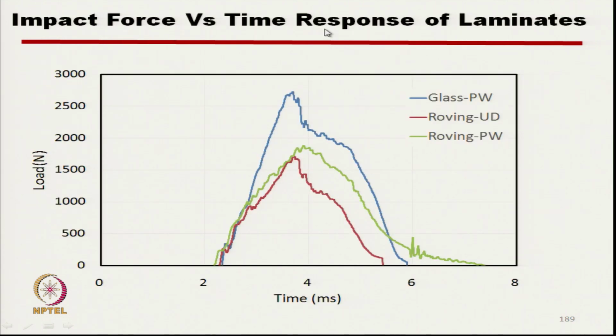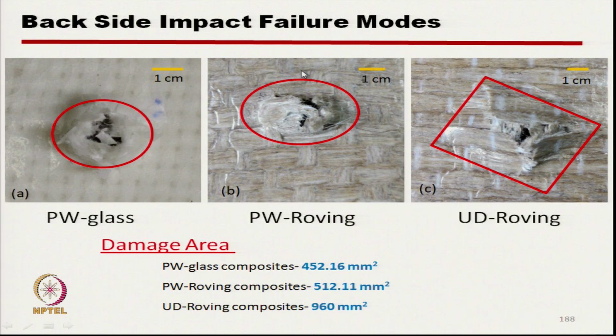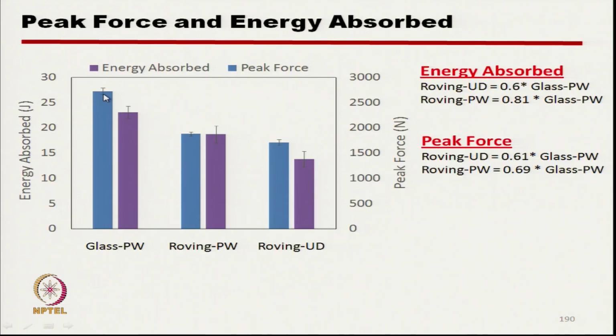In the impact load versus time response, the impact load is higher for glass, followed by plain woven roving, and unidirectional roving is behaving in an inferior manner, as we saw in the earlier picture. Unidirectional roving gives a higher damage area. Regarding peak force and energy absorption, the energy absorption of glass is much higher than the unidirectional roving composite, and it is also higher than the plain woven composite.